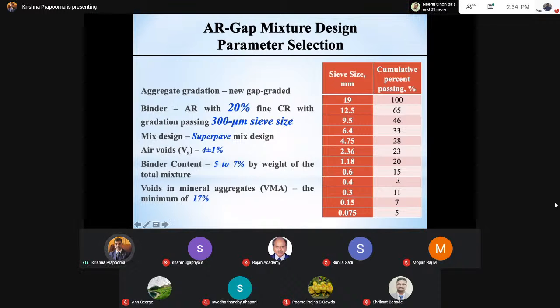Now, one other thing that you should understand is the nominal maximum aggregate size was 19 millimeter, which is a large size, obviously, and that actually helps us reap the benefits of structural capacity. So the load bearing is coming only because of the aggregate, right? And this 19 millimeter size actually helps us with that load bearing capacity. Obviously, you see that 12.5 also is of a larger number, 35% retained. So that's also in higher proportion, right?